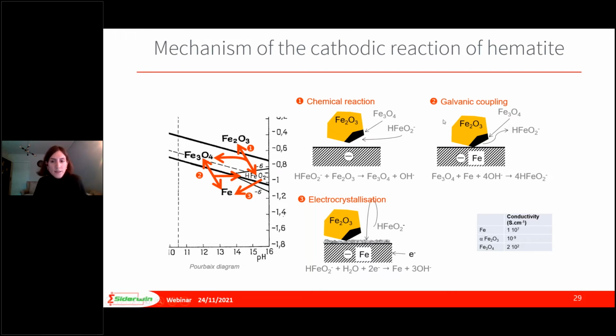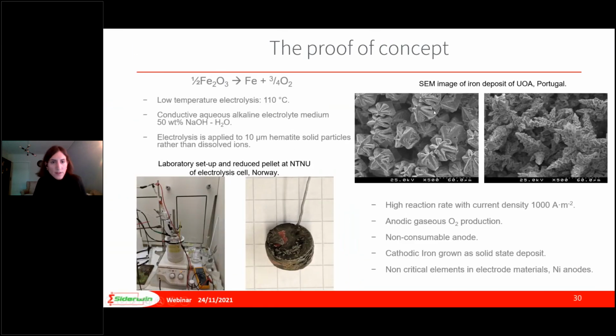During the last years, a lot of experiments took place and reconfirmed that the iron oxide reduction at lab scale is a feasible process. The experiments were conducted with 50% sodium hydroxide, as I referred earlier, and temperatures around 110 Celsius degrees. Also, the solid particle size was 10 micrometers. The anodes were made of nickel, and different types of cathodes were tested, such as stainless steel and carbon. The applied current density was 1000 ampere per square meter, and all the experiments gave high Faraday efficiencies, higher than 90%, and the cathodic iron grew as a solid-state deposit.